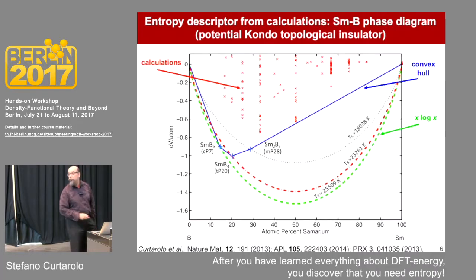We calculate the formation energy of all the phases that are fighting. Okay, don't worry about these parabolas. Just stick with the dots. The dots are possible samarium boron compounds. This is formation energy. The dots are the formation energies of potential organizations of the atoms. And thermodynamics tells you that at zero temperature you need to minimize the enthalpy. So you need to find the envelope of all these dots, the minimum points or the minimum lines. This construction is called the convex hull.